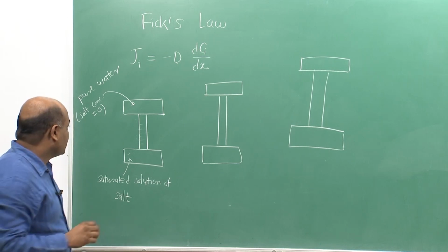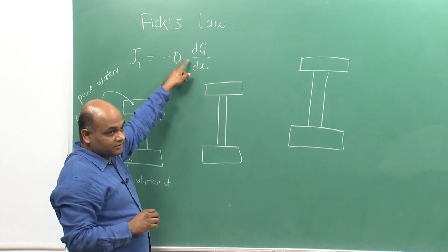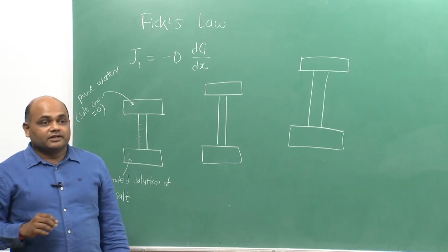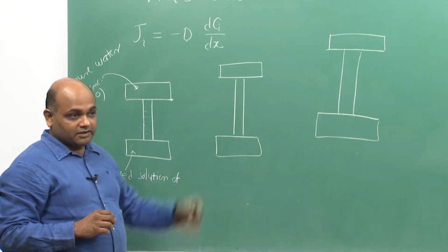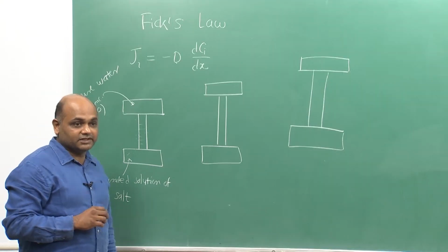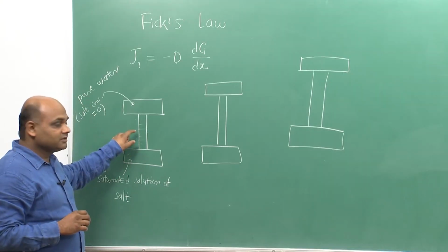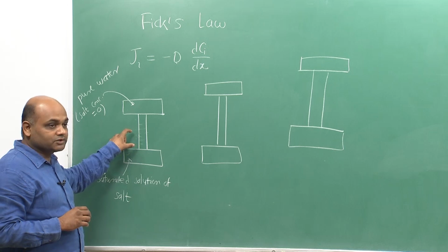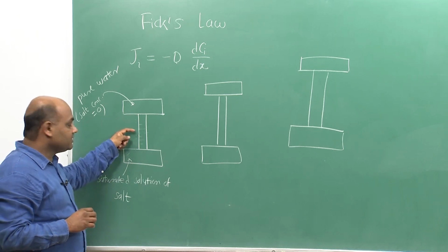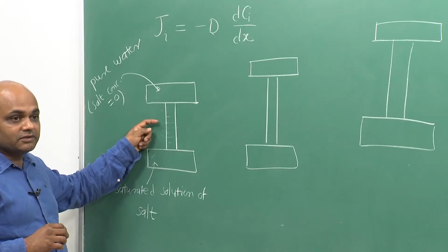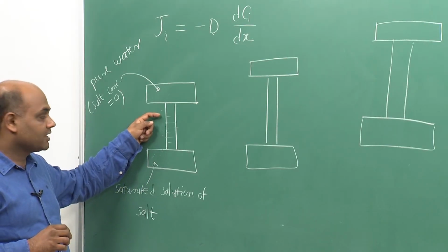So, obviously, if D is a constant or if this equation is satisfied, he should be able to measure flux in each of the cases. Now, in steady state, the flux in a given setup should be constant at any plane, right, because at any plane the matter that enters into the plane should be equal to the matter that leaves that plane.